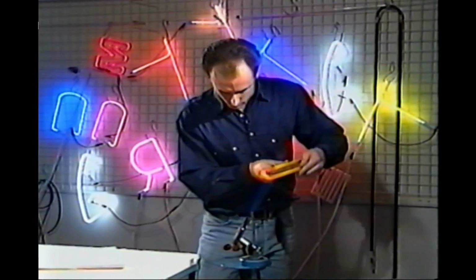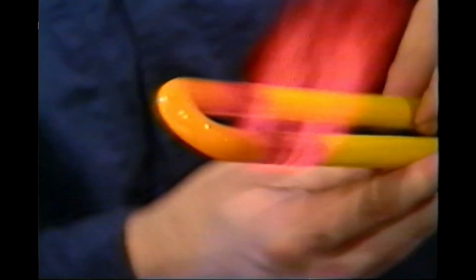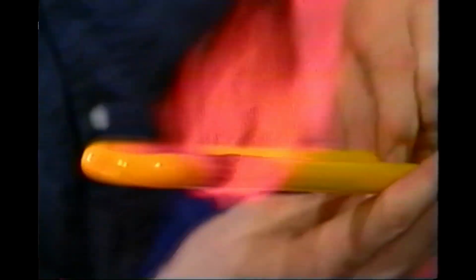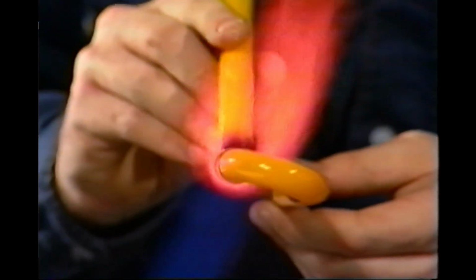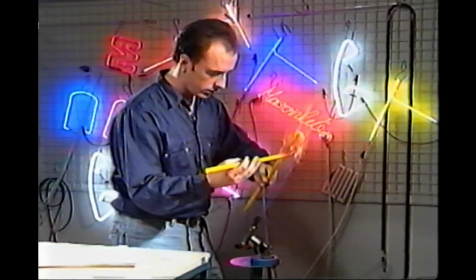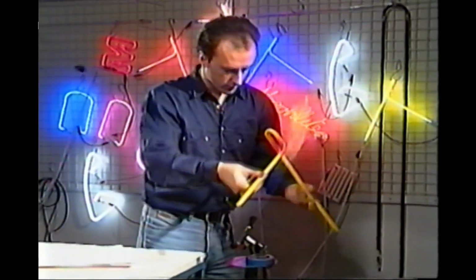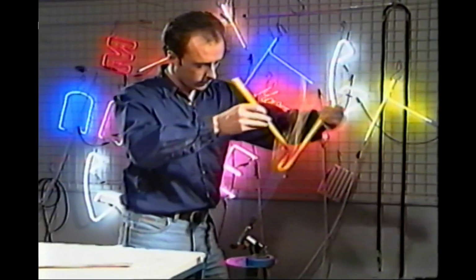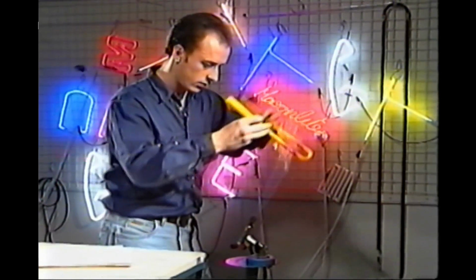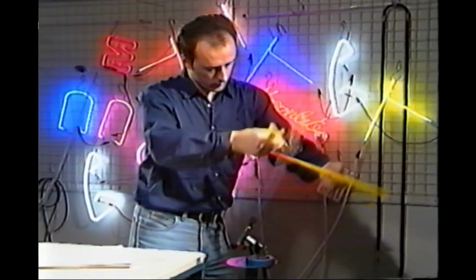Colored tubing will develop and retain more stress than lead glass. Poor heating, folded bends, twisting of the glass, severe variations in wall thickness, and contact of the hot glass on cold surfaces will cause stress, which can easily lead to cracks forming and high losses of the raw material during use. Annealing each bend immediately after forming is necessary. This gentle reheating of the glass in a large gaseous flame up to softening point takes the glass to a temperature from which stress can be released and reduced as the worked area of the tube cools evenly.